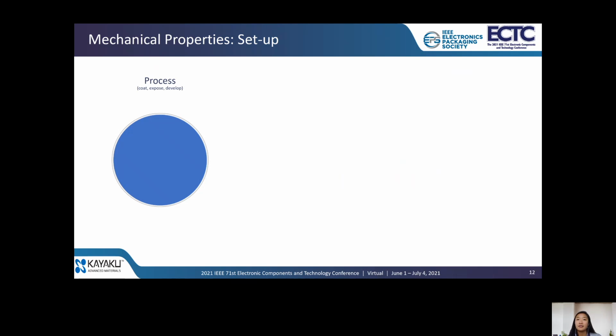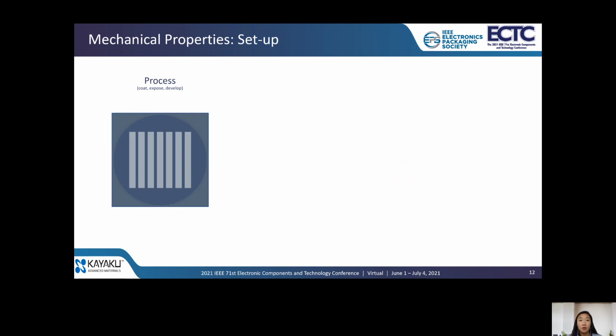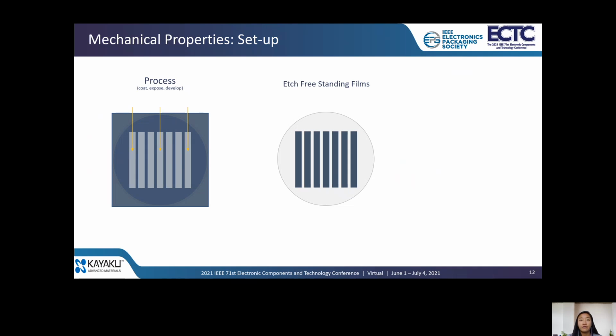So I want to go through the process that we developed at CAM to measure the mechanical properties of our permanent resists. So here we have a coated wafer with the desired resist. For us, it was PRL 29. And we coated that to a 15 micron film thickness. After soft bake, a rectangle freestanding film negative mask was used to expose and develop out the samples. After development and the cure step, the freestanding films were etched off of the silicon wafer or the desired substrate. And now our samples are really ready to test.